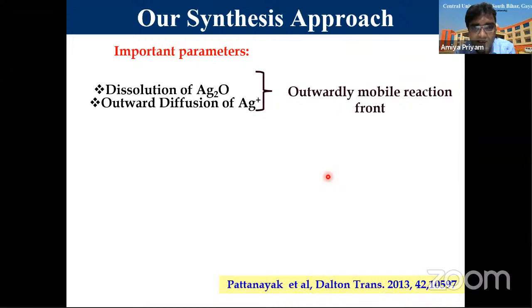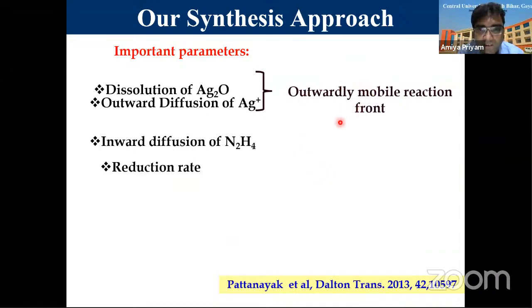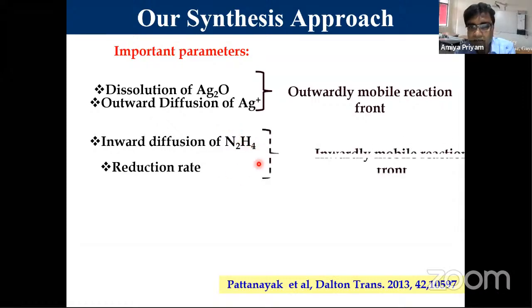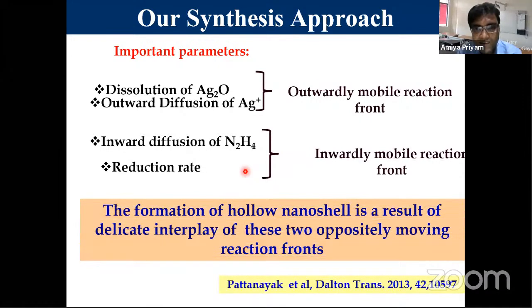So these are the events that matter in this thing: an outwardly mobile reaction front composed of dissolution of Ag2O and outward diffusion of Ag+. I just talked about that in the previous slide. And there's inward diffusion of hydrazine, and where these two meet, there will be reduction. So these are the parameters which will affect the formation, a delicate interplay of the outward mobile reaction front and the inward mobile front. When the two oppositely moving reaction fronts meet, there is a formation of hollow shell-like structures.